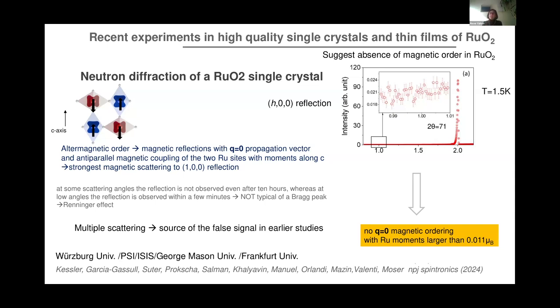So indeed, they did a very careful analysis of all these different angles. Basically what they conclude is that they are not observing Q equals 0 magnetic ordering. And let's say the upper bound that they have of magnetic moments would be 0.011 mu Bohr. In fact, they reanalyzed the data from the other paper, and that could be one of the sources of the observation of magnetic ordering in the previous neutron diffraction data: it could come from this multiple scattering. So this is one measurement that I wanted to mention.